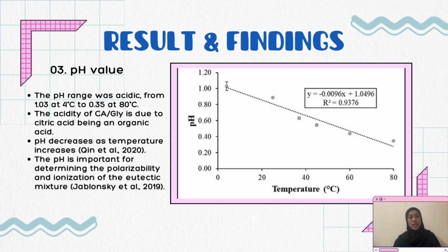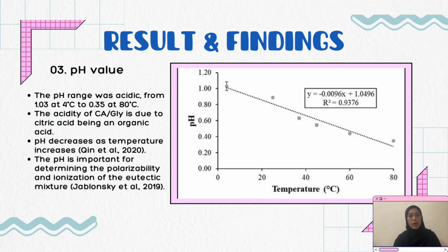Following this is the pH value. Results deem that the chosen DES is acidic in nature. This is because citric acid monohydrate is indeed an organic acid. Moreover, the increase in temperature reduces the pH value further because of the higher acid dissociation as the hydrogen bonds between the citric acid monohydrate and glycerol weaken. In terms of extraction, the acidity determines the polarizability in extracting targeted bioactive compounds.